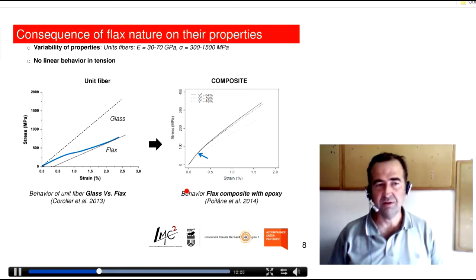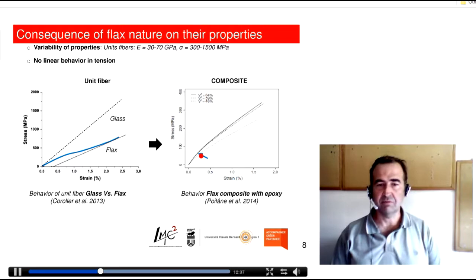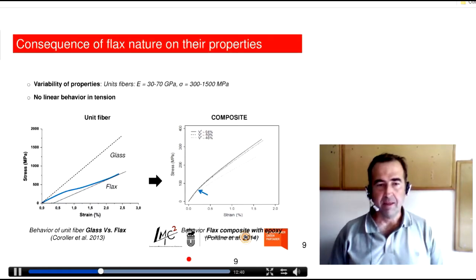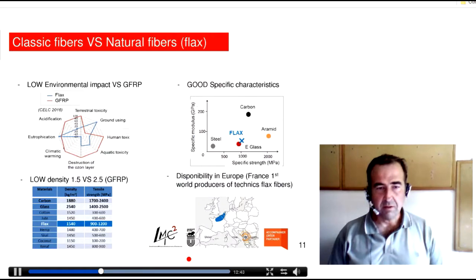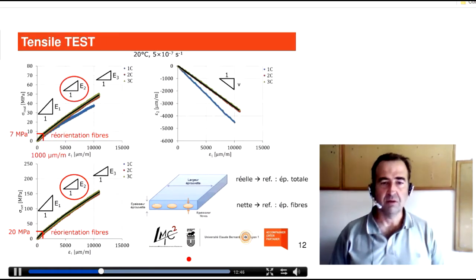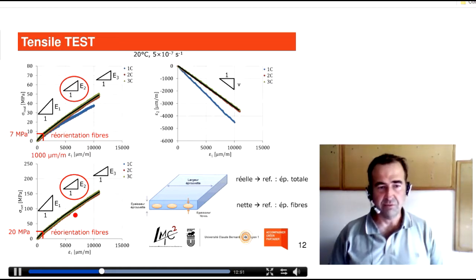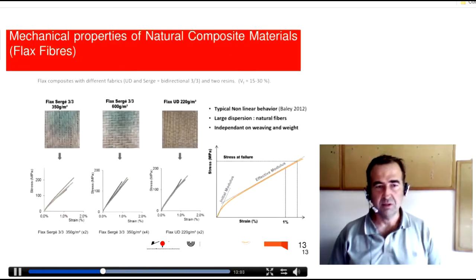And this has been well identified in the literature, where several authors have clearly shown that the mechanical properties of those fibers can be compared and obtain this kind of typical curves. Then what we've seen in the first part of the test we developed in the lab was to confirm this two-stage behavior for the flax fibers, and we also obtained several interesting results that I will develop.